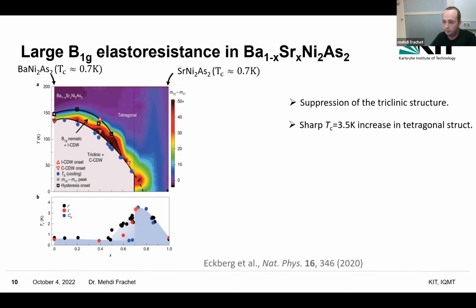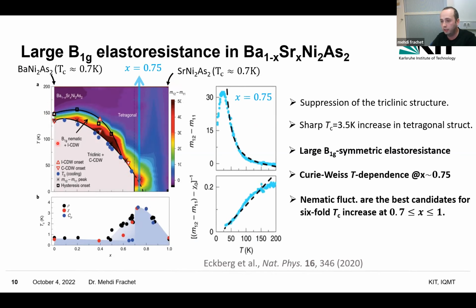And you see that just when this triclinic structure is suppressed, you have a sharp increase in TC that goes up to something like 3.5 Kelvin. So that's an elastoresistance study. And what is very important, what they uncover is actually that this material has a very large B1G symmetric elastoresistance. So that's really not a subtle effect. It's of the same amplitude as in barium iron 2 arsenic 2, for example.